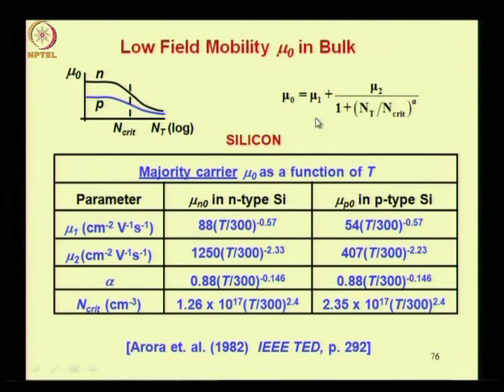One advantage of this formula, as we will see, is that it can be used for majority carrier mobility, minority carrier mobility, and for silicon, gallium arsenide, and so on. That is the advantage of this form of the equation. And also it can incorporate temperature dependence. So each of these terms, mu1, mu2 written here, you see they are temperature dependent. So this incorporates both the impurity concentration dependence, as well as temperature dependence of mobility. In case you are taking down these values, I will give you some time. I will leave the slide on for some time.